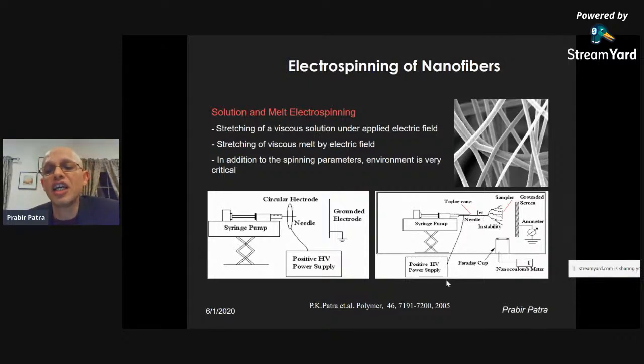We were very early in determining the charge on a single fiber. We're talking about a fiber that is 10 to 100 nanometers in diameter. Charge meaning when you're touching the needle, a tremendous amount of charge is being given to this liquid. So when they stretch to a jet formation, there is a lot of charge in it. How can you measure that charge so fast? Because this charge relaxes. The reason for measuring this charge is that when the fibers are collected, if they still have charge for a long time, then when the next batch of fibers comes, they will repel and some of the fibers will be floating in the air. We don't want that. If that happens, there'll be a lot of porosity and fiber diameter changes. We need to measure the charge, and hence we can measure how fast they relax this charge.